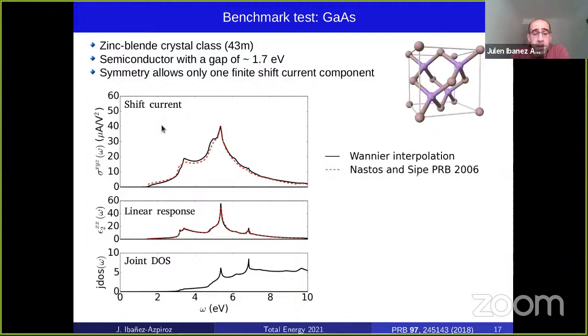So with this, I will show now results for gallium arsenide, which will then serve as a benchmark for the method. Now, in this upper panel, I'm showing the shift photoconductivity for the only component that is allowed by symmetry in this material. And I'm comparing our results with results available in the literature. Now, the comparison is good, but for reference here, I included also the calculation of the linear response. And we see that the agreement between the two results is very similar in both cases, which makes us confident about the method.